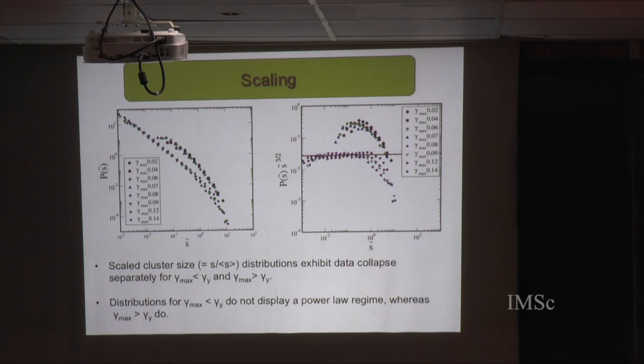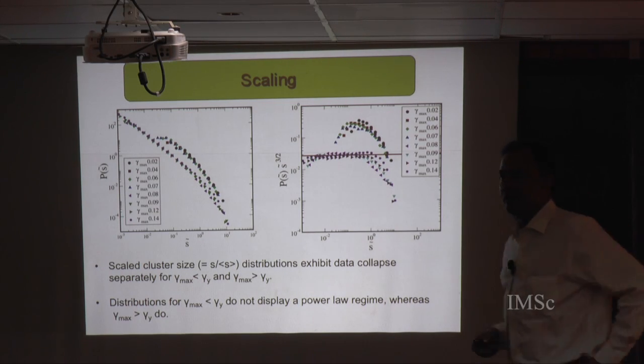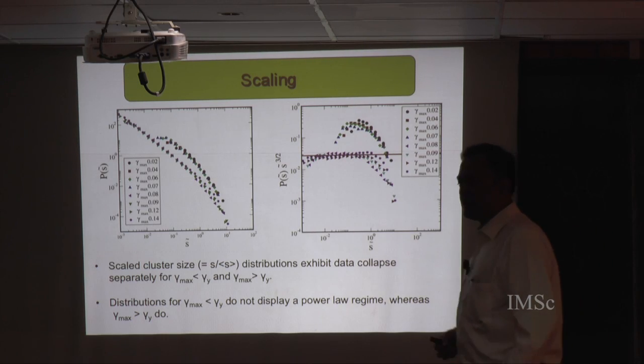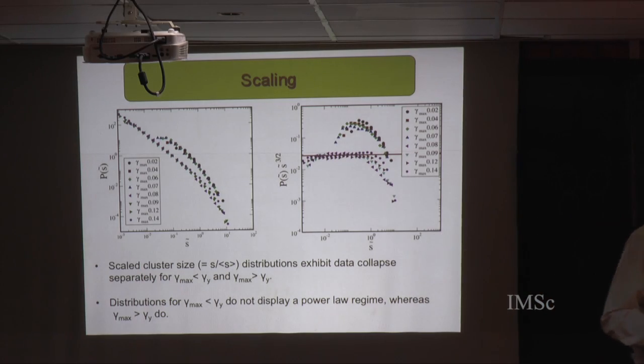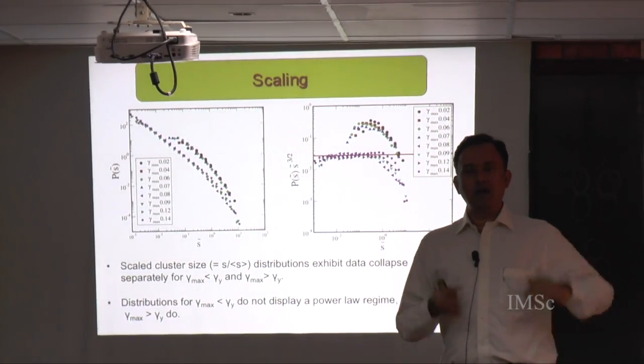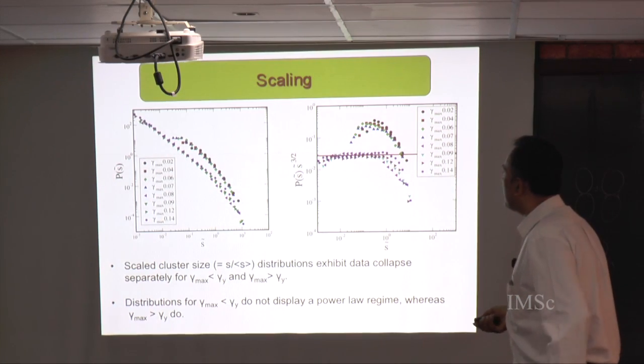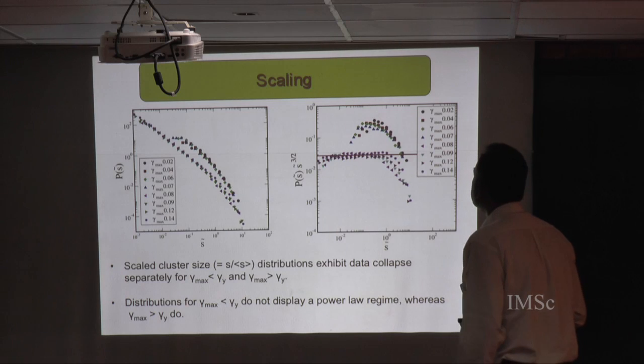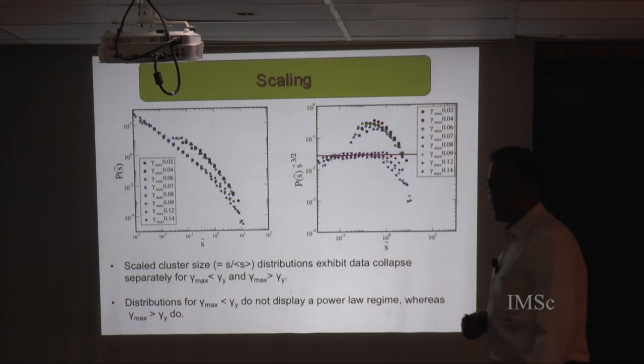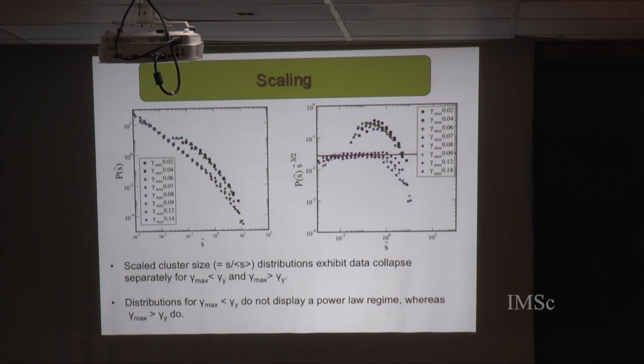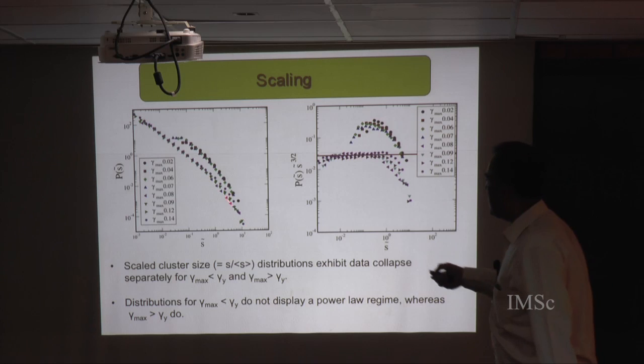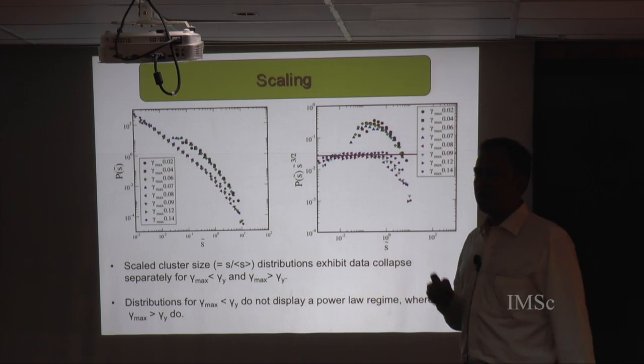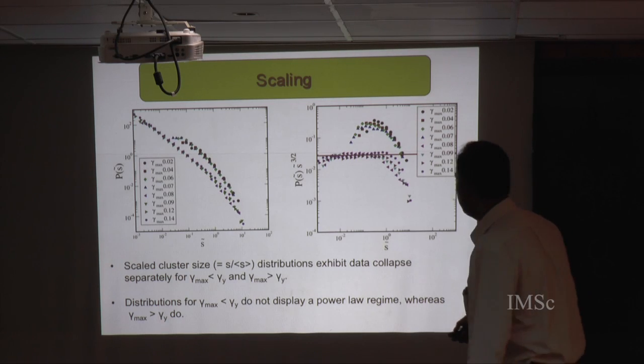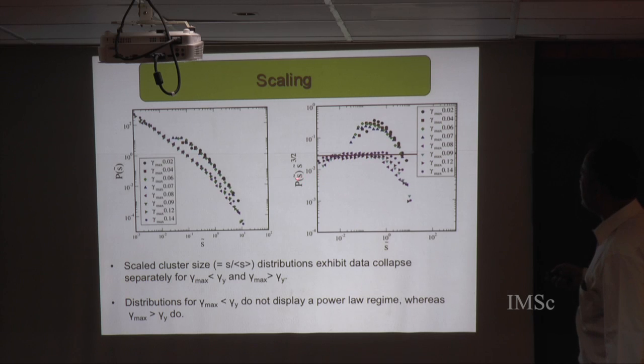Okay, so here is something again more interesting. Because we look so far at the mean cluster sizes, we can ask, is that sort of a good enough number with which to scale the data and obtain sort of a common scaling behavior? And the quick answer is yes. But interestingly, you have avalanche size distributions which fall on these scaling functions that are different above and below the yielding transition. Okay, so this is sort of highlighted by dividing out by s to the 3/2, which is sort of the expected power law behavior.